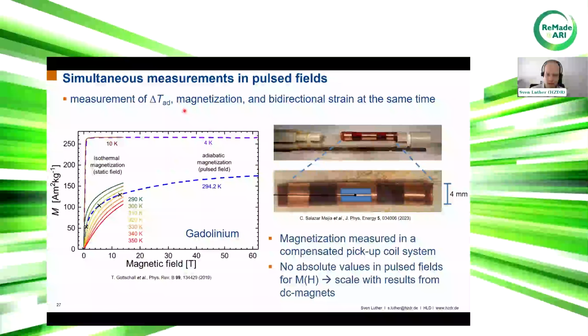In addition, we can not only measure the magnetocaloric effect, we can also measure in parallel the magnetization of the sample. You can see this is a kind of home-built pickup coil system, which is a compensated pickup coil. The sandwich sample would sit inside this coil, which is our magnetization pickup coil, where we again measure a voltage change coming from the change of the magnetization of the sample by applying magnetic fields.